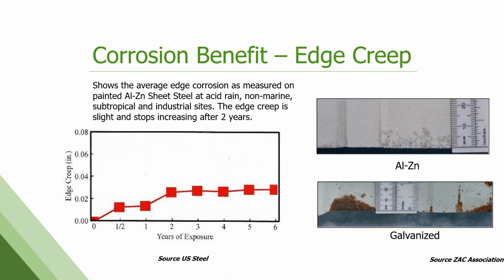And like I mentioned before, is there corrosion going on with the aluminum zinc product? Yes, there is, but it's severely retarded and mitigated versus the galvanized. And what we see in the real world too is that galvanized in the first, I'd say 5 to 7 years, might perform the same as the aluminum zinc, but then an inversion takes place. The galvanized continues to corrode and the aluminum zinc product stops and slows down. So we get this reverse effect after a few years.